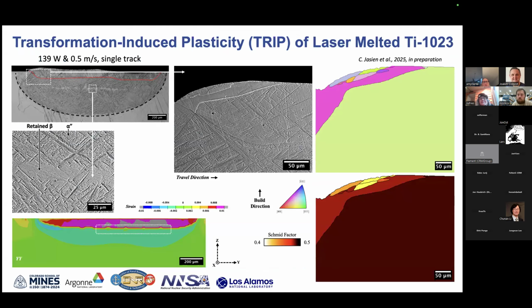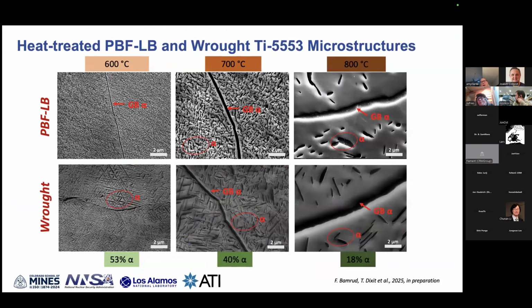One of my students, Chris, did quite a bit of work trying to understand the propensity for deformation-induced martensite in these metastable beta Ti alloys. This is an example of a track melt and then a subsurface region where we had retained beta phase. He did a lot of modeling trying to understand those local conditions and why we do or don't get phase transformation. Coupled with that, he was also looking at things like grain size effects and orientation effects in terms of the propensity for transformation in the beta alloys.